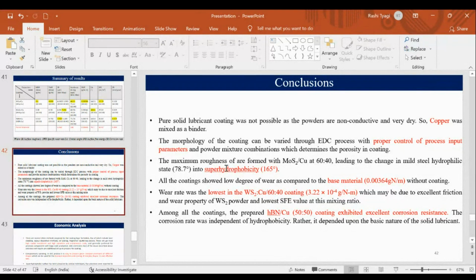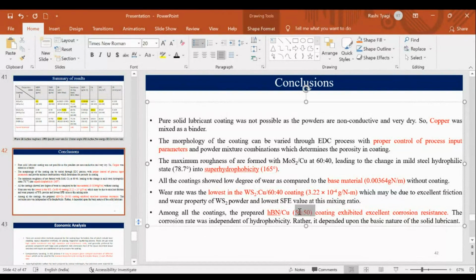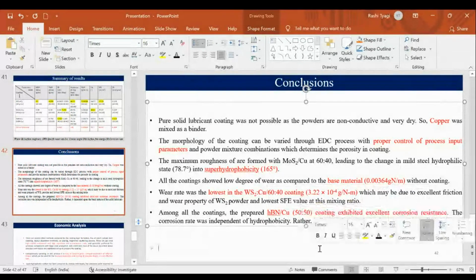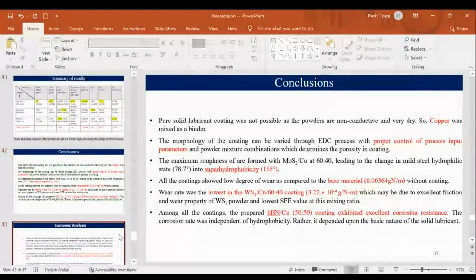Also, the super hydrophobic coating is obtained, which changes the hydrophilic state of the mild steel parent material into super hydrophobic. All these coatings show a low degree of wear as compared to the parent material, and the wear rate was lowest for WS2 copper coating. Why? I have also showed you there may be some relation between surface free energy and WS2 plus copper coating, because surface free energy is lower for this coating, so it showed lower wear. Also, corrosion resistance is higher for HBN plus copper coating, as HBN is a corrosion resistant material, so it will provide high corrosion resistance.